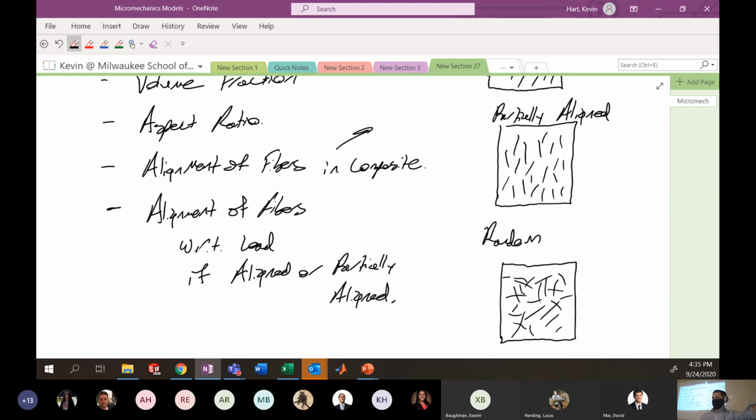I should say that these models are actually quite complicated. When you're including short fibers in a matrix, there are certain limitations and mechanical responses at the ends of the fibers that are rather complicated. In the middle of a long fiber, you can hold tension and compression relatively easily inside a composite. At the ends of the fiber, you don't really hold any normal stress because you don't have fiber there to hold it. So the models are much more complicated.